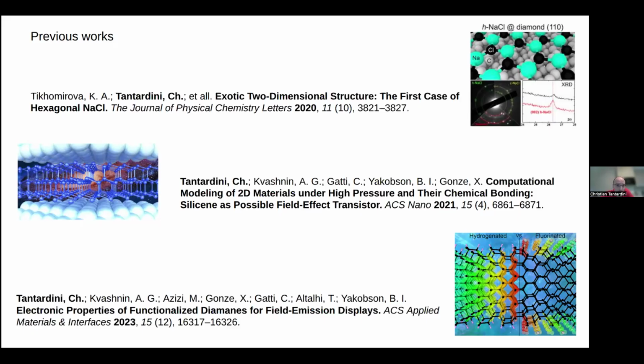Also, we have worked, for example, in high pressure, and this was developing the code to model the uniaxial pressure, actually introducing this stress tensor and being allowed to have not only hydrostatic pressure. And we have looked at how silicene can be a possible field effect transistor. So by changing the uniaxial pressure, we change the hybridization of our silicene, and we got new electronic properties.